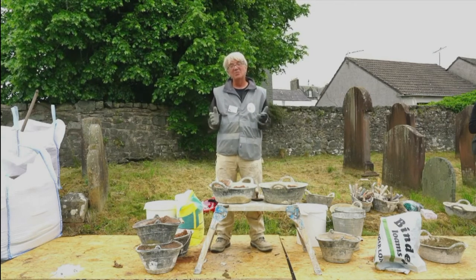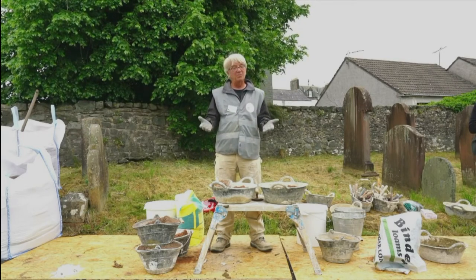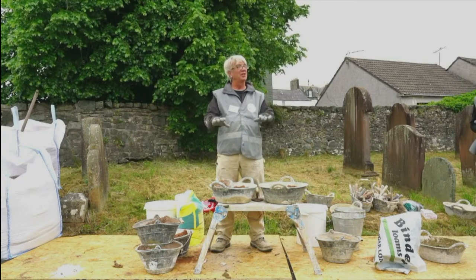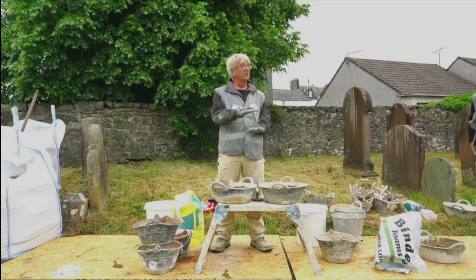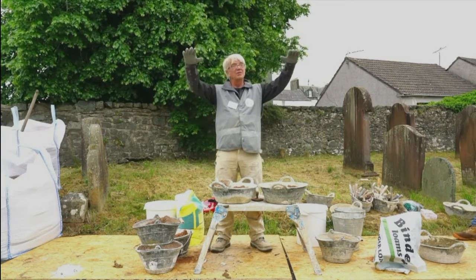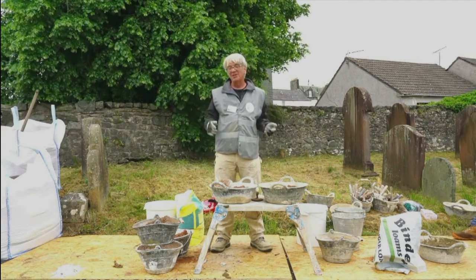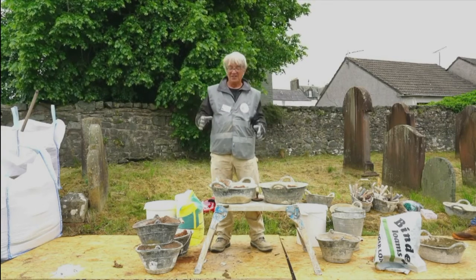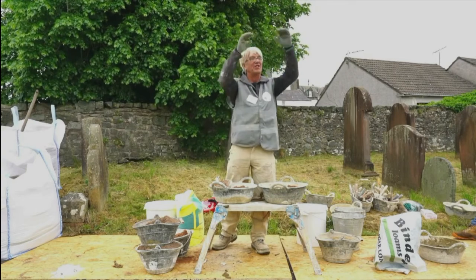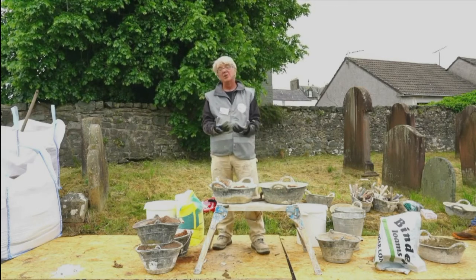It's not that different with NHLs, but in the old paradigm, I would call it, the idea was the only way you could build a flint wall was to use a fast-setting hydraulic material that sets fast enough that you can keep building. But even then, they actually start to swim around within a couple of courses. If you were to use a hot mix, you could build the whole wall in a day. I can tell you that with absolute certainty. When we did the hot mix event at Canterbury, we were just messing around, but Rory Young built a spire of flint that high in five minutes. And it's all there, and it's not swimming, it's not moving, it's stiffening, because that's what hot mixes do, particularly if you get them in hot.